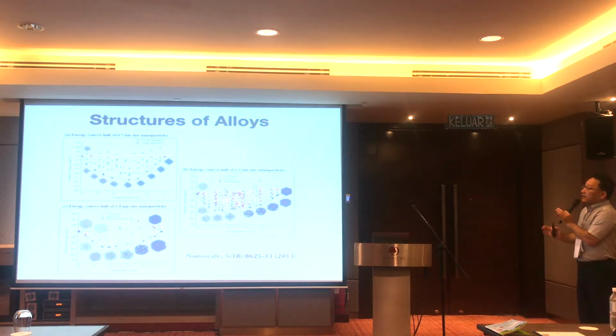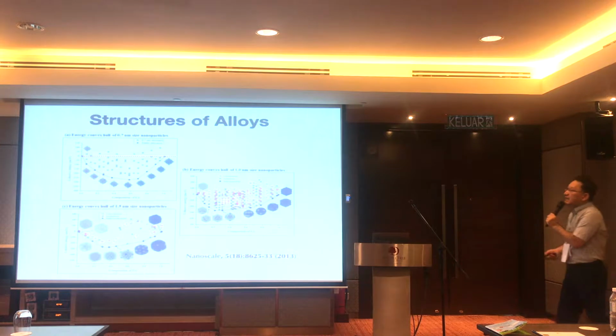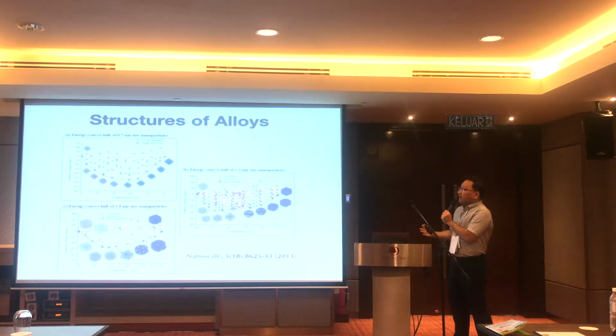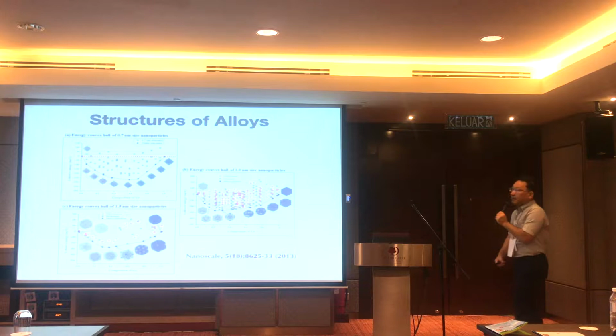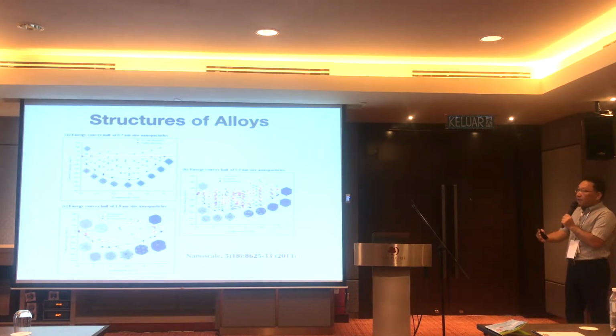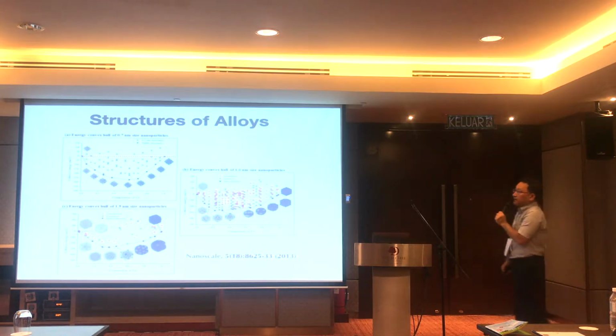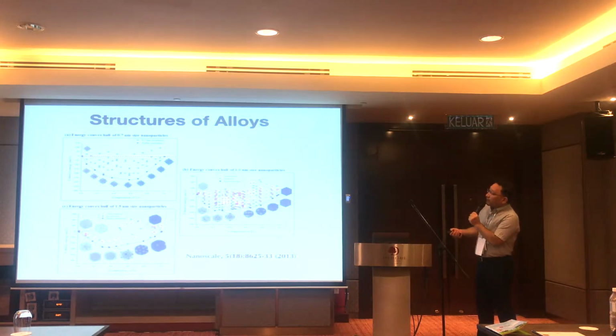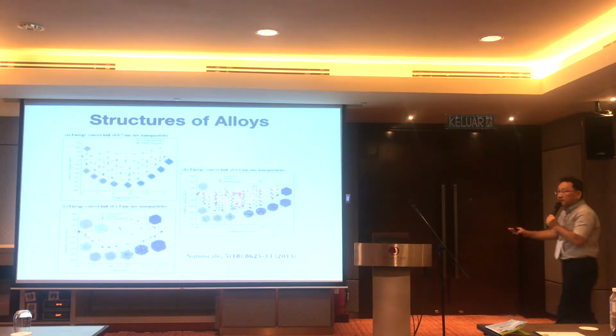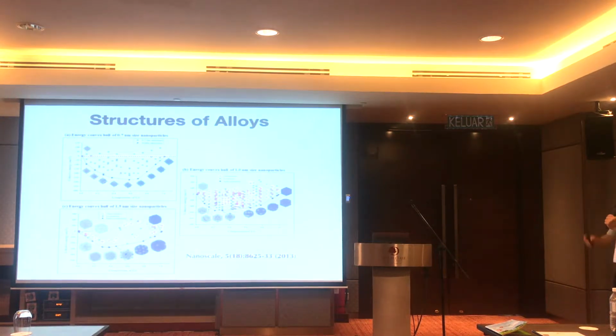How about alloys? Typical alloys in the nanoparticle sectors. We can screen them here. We have thousands of material candidates. You can quickly calculate if you are assigned: can you predict, let's say, platinum, nickel, or cobalt, the most stable structure? Of course, you can do it by computational screening. We have thousands of typical candidates, and you can sort out the most stable configurations as a function of alloy composition very easily, very quickly. And you can provide this database of information to experimentalists. Can you design this material? Of course. Some experimentalists want to design, for example, these materials. Certain compositions you cannot design because they are not stable. Just forget about it. Then experimentalists can save their money and time.